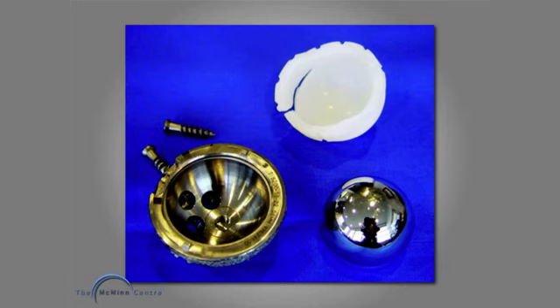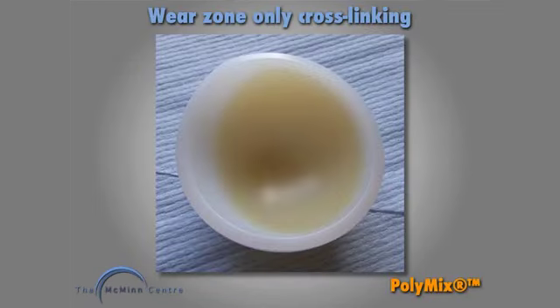The mechanical properties of cross-linked polyethylene have been seen, and there have been a few publications where we have a thin cross-linked polyethylene liner and a vertically inclined cup, and there's been fracture of the superior edge of the cup. What I've been working with polymer chemists on over the past 3+ years is getting a hybrid polyethylene where you can see the darker zone is the cross-linked area and the whiter periphery is conventional polyethylene that has been molded to the cross-linked polyethylene to give good mechanical properties on the edge. So I think we can get the best of both worlds here. We can get the wear resistance from cross-linked polyethylene, but avoid the hazard of weaker cross-linked polyethylene around the edge of the cup.